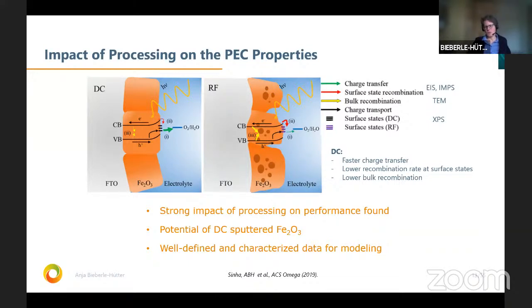The other thing that we learn is also that you really have to look in detail at the processing conditions, and that a lot of differences in the literature, also on different behavior, or when you look at the surface states or things like this, the processing was always done differently. So it is good also to compare, in this way, in one study where you do the same analysis. And this is for sure important when we see later, when we go to modeling, that we have well-defined and well-characterized data for the modeling, where we know what all the structural morphological properties are.